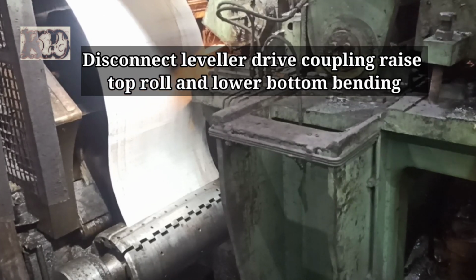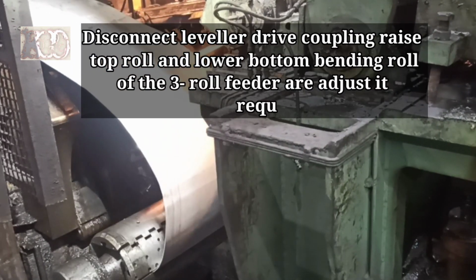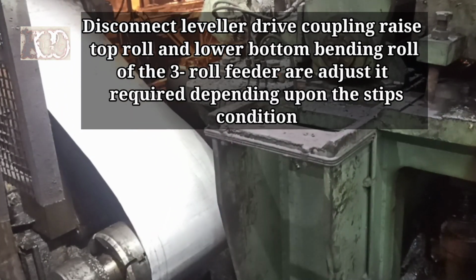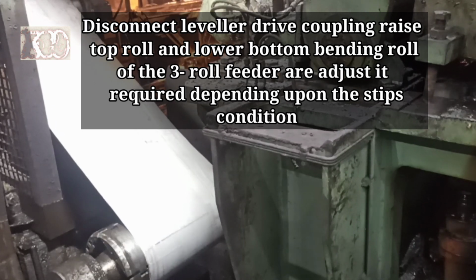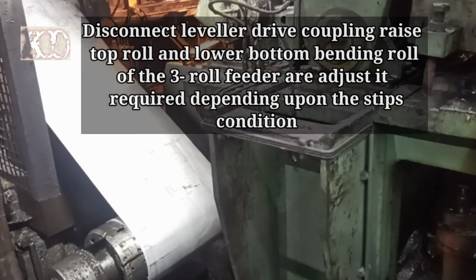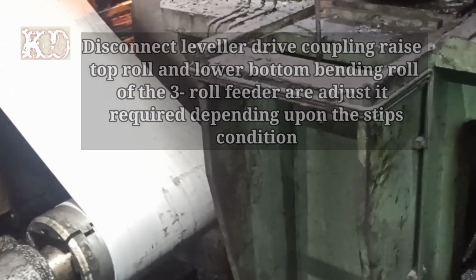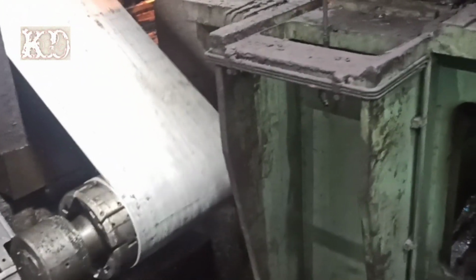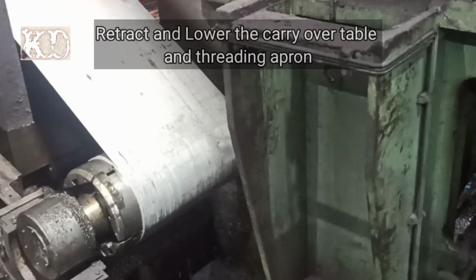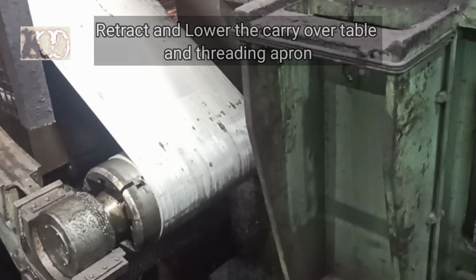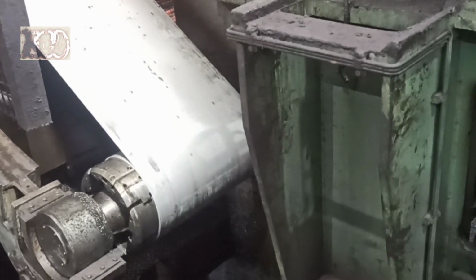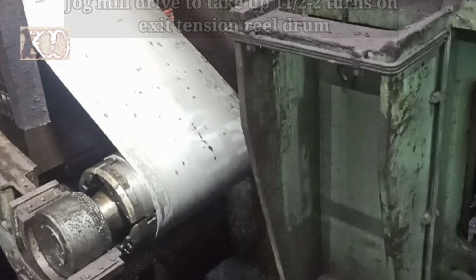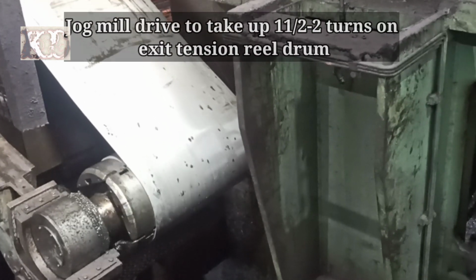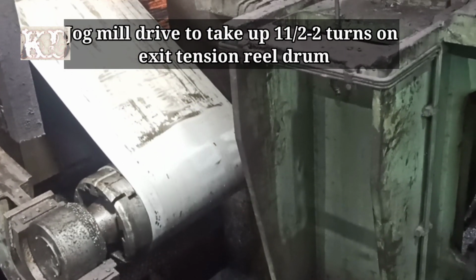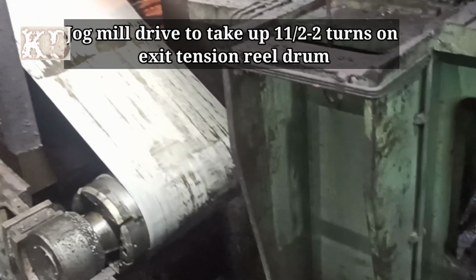Disconnect leveler drive coupling. Raise top roll and lower bottom bending roll of the 3-roll feeder, adjusted as required depending upon the strip's condition. Retract and lower the carryover table and the threading apron. Jog mill drive to take up 1 1/2 to 2 turns on the exit tension reel drum.